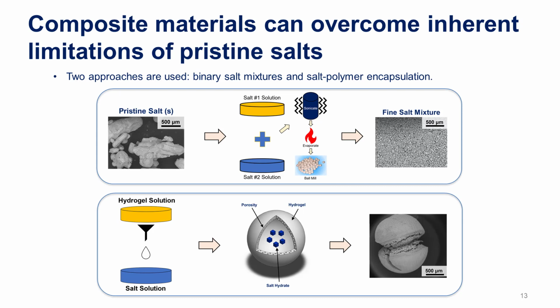And here's an SEM image of some of the initial beads that we've made, and you can see the porous structure within this. In this case, it's an alginate hydrogel, and the salt is held within the bead. By physically holding the salt in place, it prevents it from breaking down and forming salt solution, and that really helps us get a much more stable material to work with, as well as introduces this porosity so that you can get fast kinetics during hydration and dehydration. So this is ongoing work.